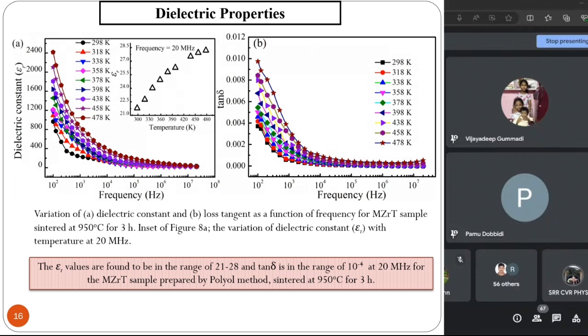Because the silver electrodes also will contribute. At temperature, silver will diffuse into a little bit of porosity, and it will also try to enhance the loss factor at lower frequencies. But when we do microwave measurements, you don't have to apply the silver paint there. It is a polished ceramic disc straight away. Okay, that is the resonant method.